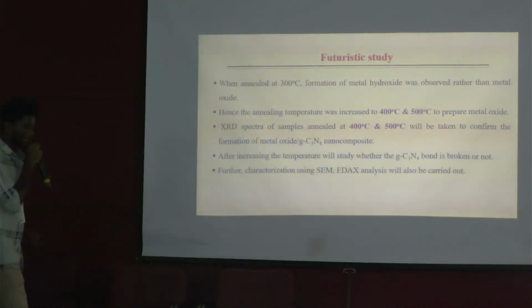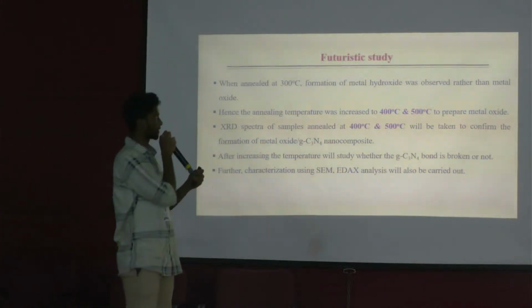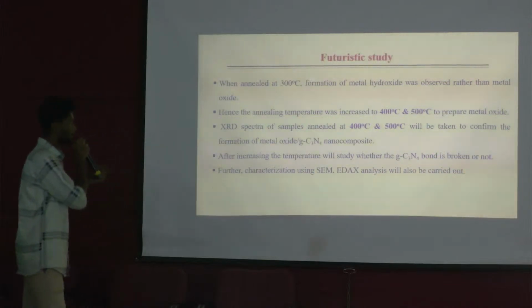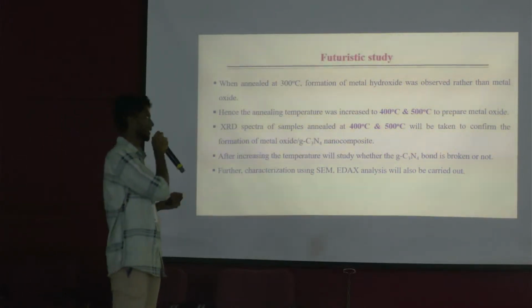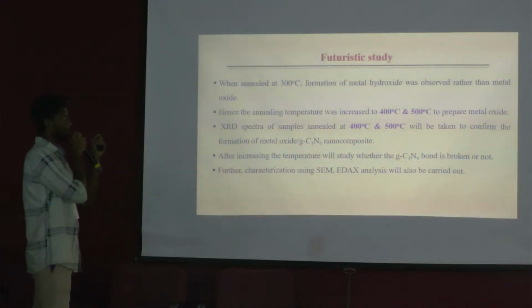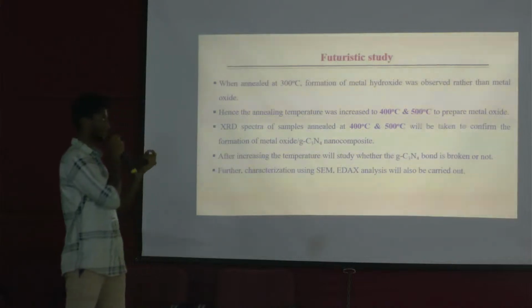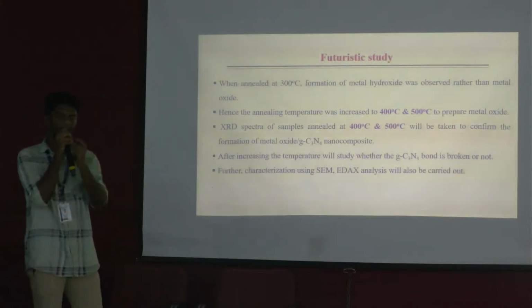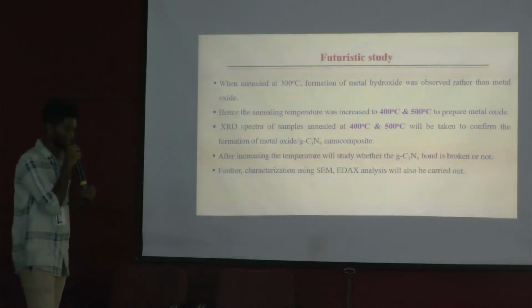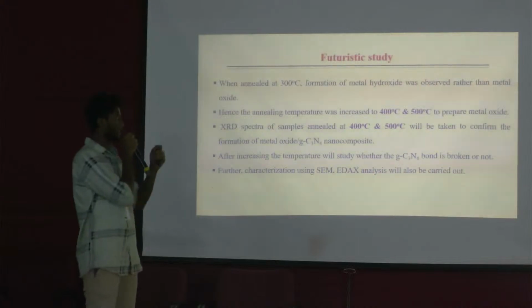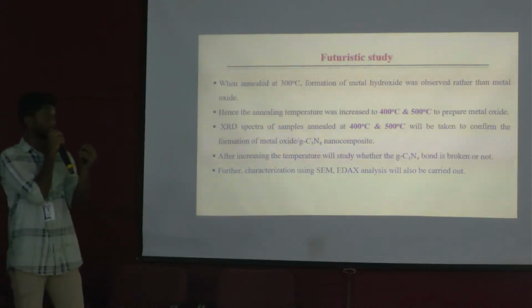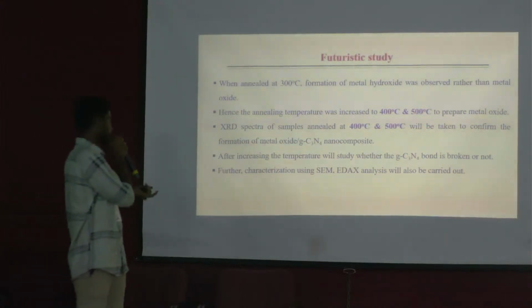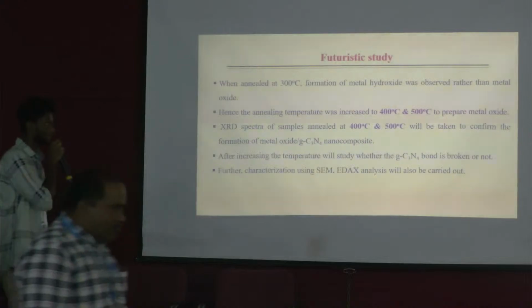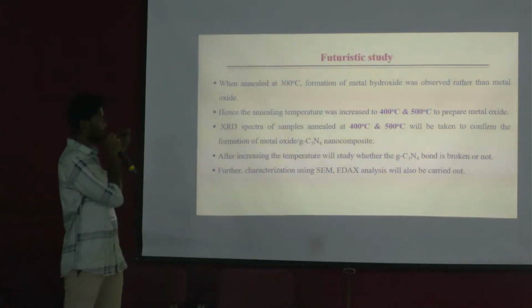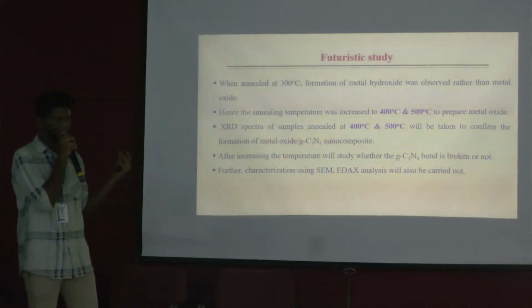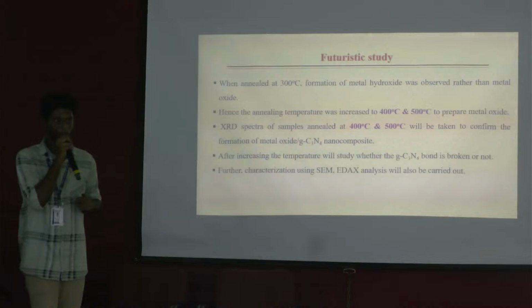Future study: when annealed at 300 degrees Celsius, formation of metal hydroxide was observed rather than the metal oxide bond. Hence, the annealing temperature was increased to 400 and 500 degrees Celsius to prepare the metal oxide. XRD spectra of samples annealed at 400 and 500 degrees Celsius will be taken to confirm the formation of the metal oxide and graphitic carbon nitride nanocomposite. We would also like to analyze, after increasing the temperature, whether the graphitic carbon nitride bond is broken or not. Further SEM and EDAX analysis will also be carried out, for the structural composition, morphology and elements present in our compound.